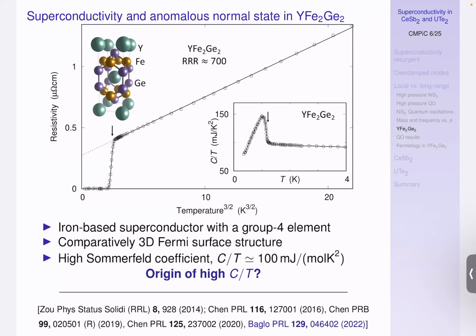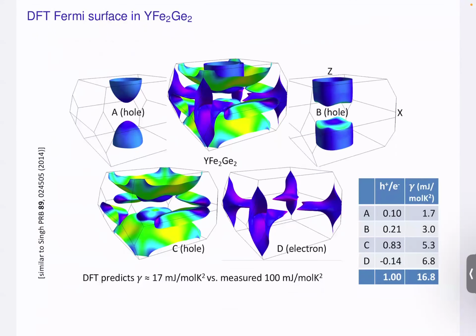So after we were able to make good crystals, the question was, okay, can we map out the Fermi surface? The Fermi surface looks quite different from other iron-based superconductors. Most iron-based superconductors are highly layered, very two-dimensional, so the Fermi surface is made from cylinders. Here, DFT calculations say it's very three-dimensional. You have these ellipsoidal pockets, one small, one larger, then a big one here, which looks almost like a pillow. And then you have electron pockets on the corner, which may have these noses sticking out towards the center.